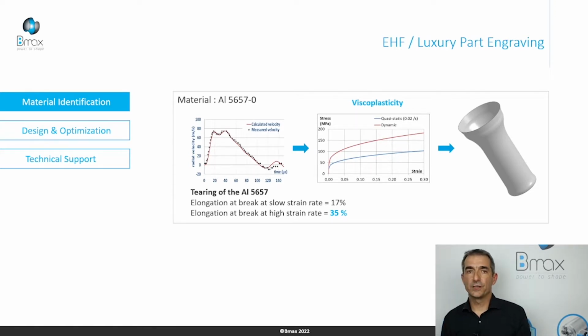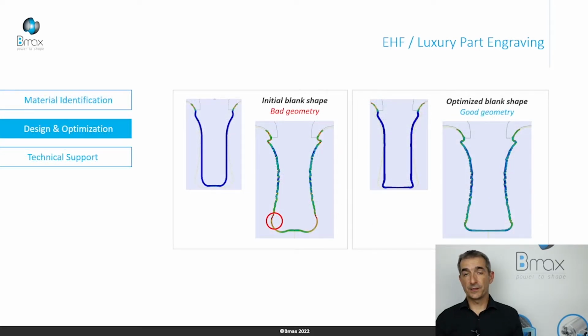After, we perform 2D simulation to optimize the conditions to maximize the efficiency of the EHF process. On the left side, it's a very simple preform geometry. And as we can see, at the bottom of this sample, we create a necking, excessive thinning, and there is a very significant risk of crack. So the iteration consists of creating a bump in the bottom of this sample to have extra material. In this way, we have a good process, a good deformation during the process, and the corner of the blank matches the corner of the die.